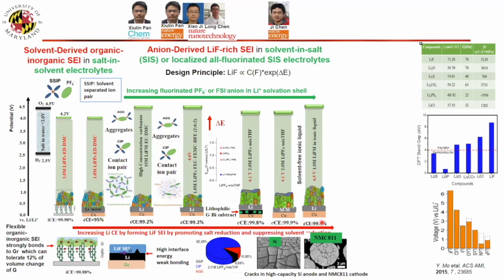even at high capacity, 5 mAh/cm². So from this, we think the solvent is really not good for a high-capacity electrode, because the volume change is really big.